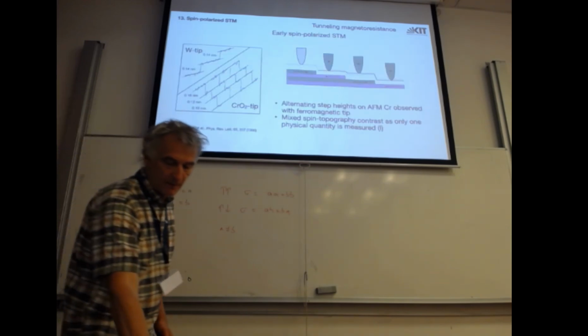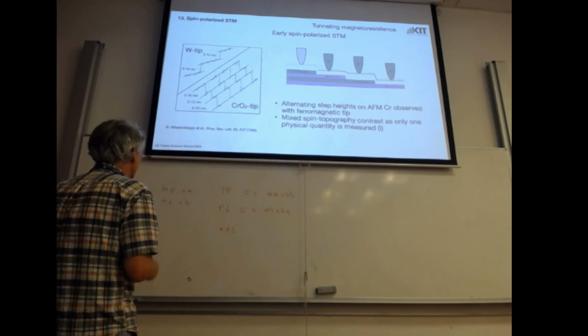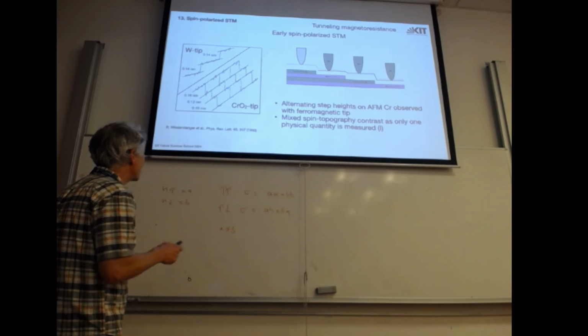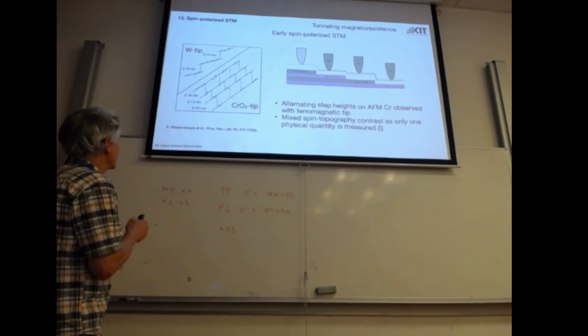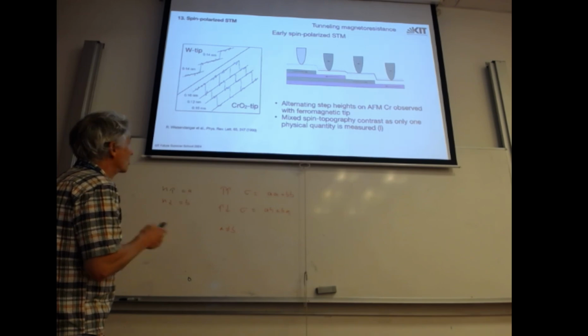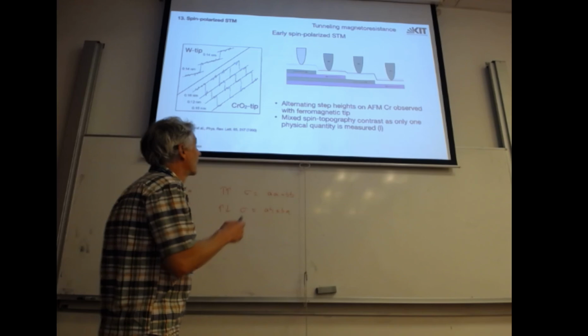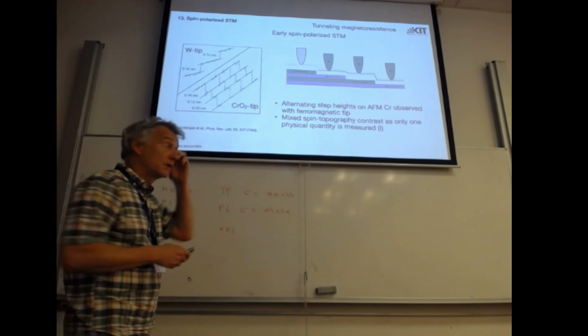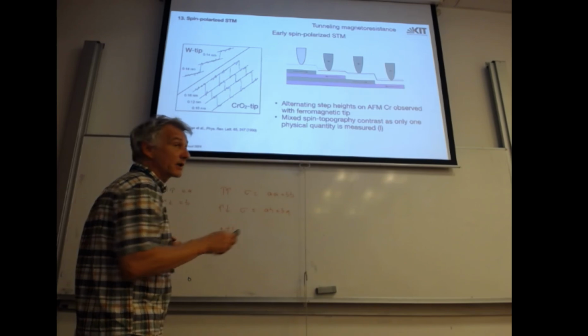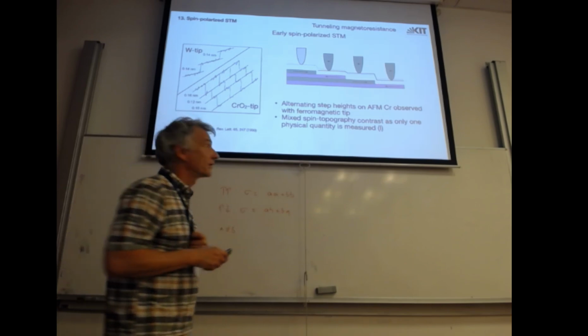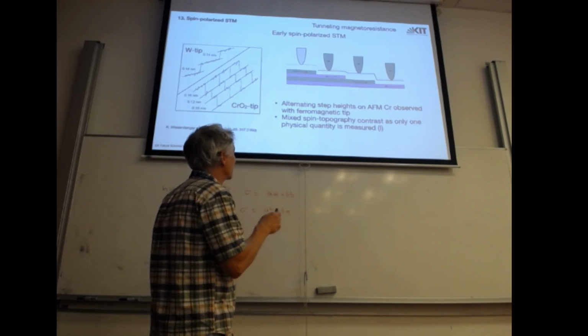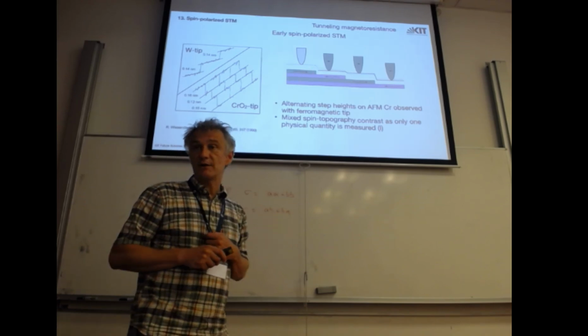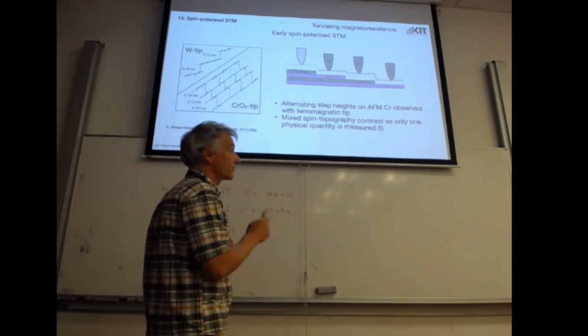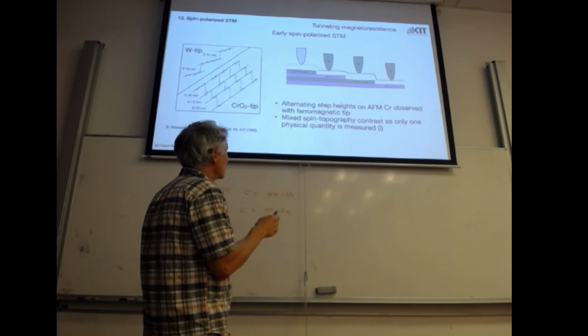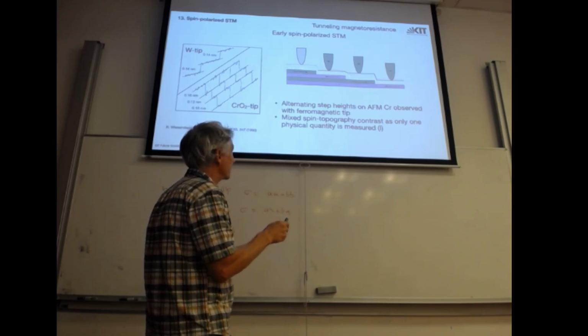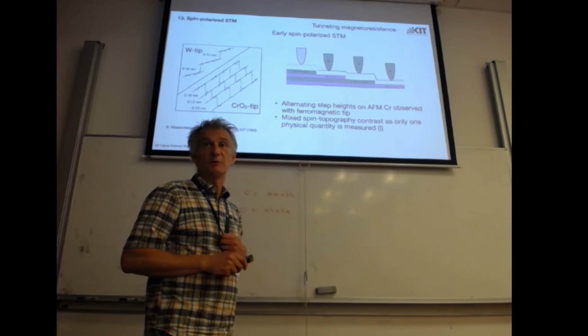And this was first experimentally realized by Wulfhekel in this paper, and he used chromium, an antiferromagnet, and a tungsten tip, and went here with constant current over these atomic steps. Now the density of states does not matter. It does not care what the direction of the local magnetization is. It's the same density, but just the spin is in a different direction. So the tip will follow just the topography of this problem.